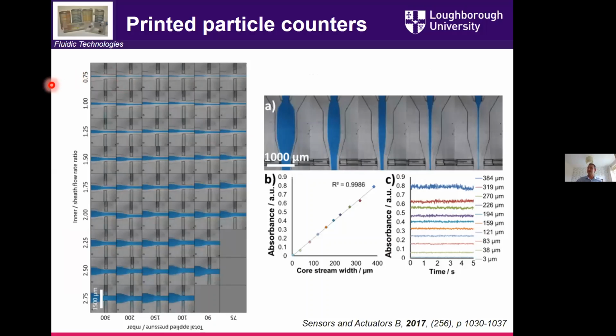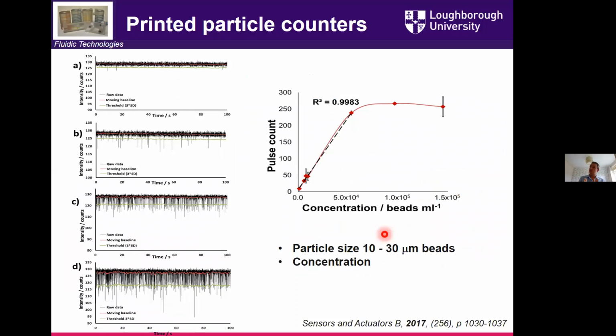So you can go all the way from a couple of microns to a whole wide range of, if you like, feed stream, those droplets coming through. And you get information, as you would expect, in terms of the absorbance, the different wavelengths. You can validate what the core stream width is. And so we wanted to make sure that we could control the thickness and the number of droplets, but also get some other information. And so, yes, you can get optical measurements, but you can also get some information on the size of the droplet.